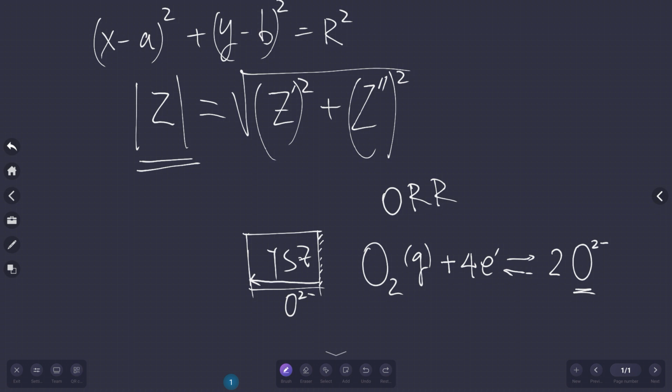Remember we talked about this Brouwer diagram? There is a large range of pO2 where this material will remain a 100% oxygen ion conductor, and that's your electrolyte here. So you can see that for this oxygen reduction reaction to happen, where does it happen? It happens at the triple phase boundary, TPB. Well, what are the triple phases?